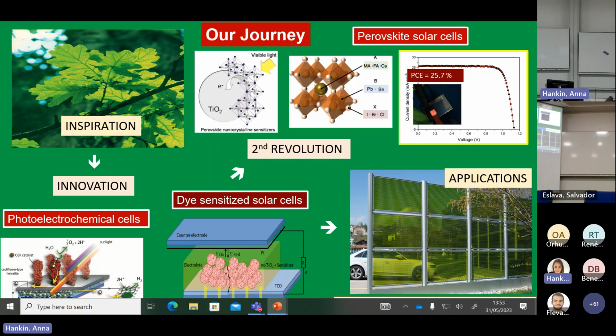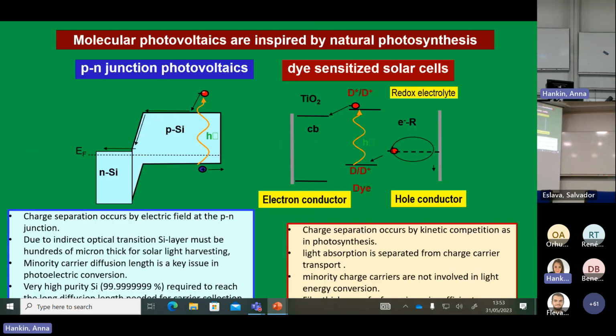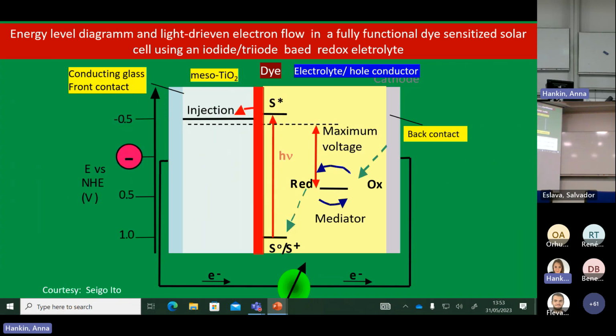And we'll also be seeing what people call the second revolution, the advent of the perovskites and also some applications. As I said, in the dye-sensitized cell, you don't use a p-n junction. We have the sensitizer as a monolayer between an electron-selective and a hole-selective contact. If we set that in motion with the injection process and electron-selective contacts, and you do work with the electron, you have to bring it back to the dye. So you need some shuttle that brings it back, which could be a hole conductor or a redox couple. And so there's a solid-phase version and a liquid version of the dye-sensitized cell.